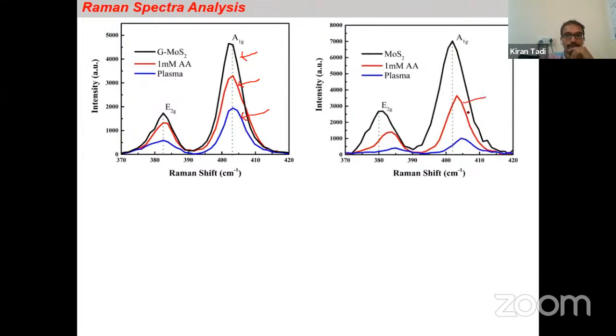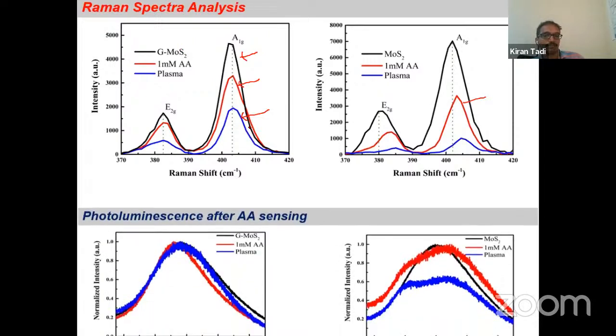This is ascorbic acid interacted, this is plasma interacted. You can see here there is a shift in the MoS2 peaks, showing that the structure has been disturbed, whereas in the graphene-protected layer, the structure is not disturbed in this case.